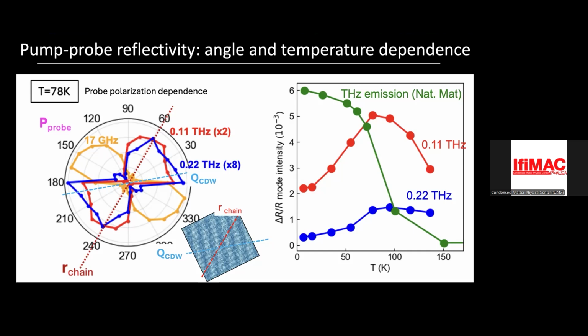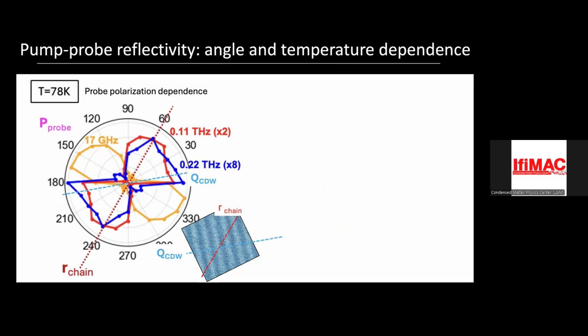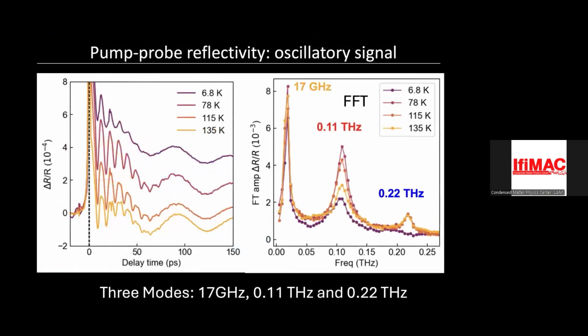So X-ray studies that see the amplitude mode, they see this thing, right? This temperature dependence is exactly the opposite of what you would expect for the phason. So it all rests on this temperature. And the peak at 0.22 should be understood as the second harmonic of the amplitude mode. It's very tiny, and in fact almost zero for most of it. Let me show you the data. It's very difficult to see this peak, and it's behaving like you would expect a second harmonic.